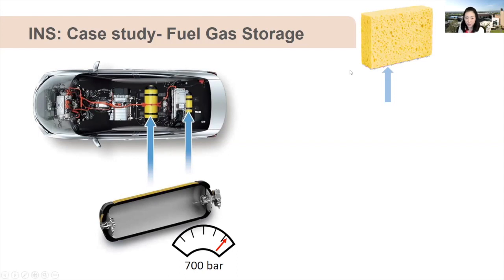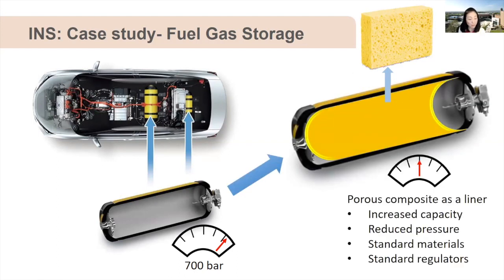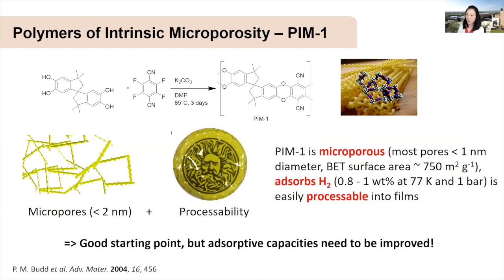So based on this conclusion, we developed a porous composite as a liner for the hydrogen storage tank in order to increase its capacity and reduce the pressure, so that we can use more standard material and regulator and reduce the tank's cost. We selected the polymer of intrinsic microporosity, PIM-1, a very interesting porous polymer. It can be processed into a membrane. You can see this yellow transparent membrane is the PIM-1 membrane. It has microporosity with most pores less than 1 nanometer, and this ticks our optimal pore size box.